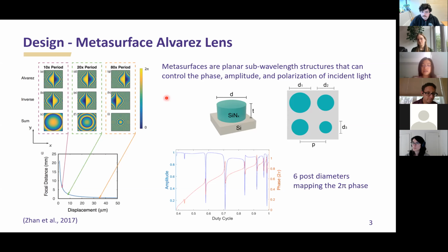And in this case, we can convert the 3D Alvarez optics elements, which were shown before, into a pair of 2D metasurface optics. So Lucas was talking about his 3D meta-material. You can think of a metasurface as a 2D material in which the thickness is negligible. So crush the 3D material down, and we have a 2D metasurface. And in this case, we are designing a pair of 2D Alvarez metasurfaces with a complementary cubic phase surface profile.